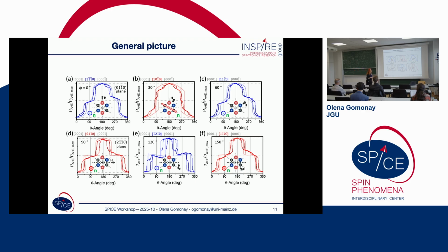So this is a general picture which we got using these very thin electrodes. What you can see here is that all the curves are very different, in contrast to the previous slide where all the curves were identical. The difference between these curves is the orientation of the Hall bar with respect to the crystallographic axis. It's schematically shown here. So it's the same Hall bar, but a different plane in which I rotate the magnetic field, as shown here. Here the magnetic field is rotated within this plane, here within this plane, and so on. So 6 different possibilities which should cover the initial hexagonal crystallographic symmetry.